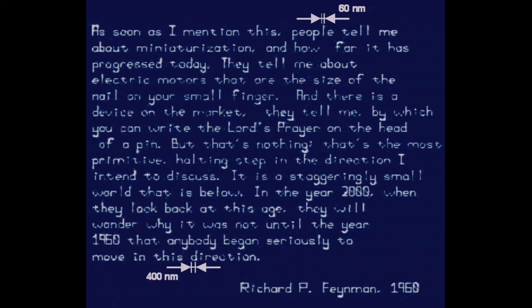We wanted to prove that we could have the control that was necessary to truly turn this into a lithography. So I told the students, let's go back to Feynman's speech and print it with molecules. What you're looking at is not a print on paper, it's a print on gold. The white letters are one molecule high, and the image here is a false color map. The tip comes along and we measure the friction, and the molecules that cover the gold substrate in this case create a high friction area, and the tip sticks, giving you this frictional force map that you're observing here. And it's kind of neat if you read this paragraph.